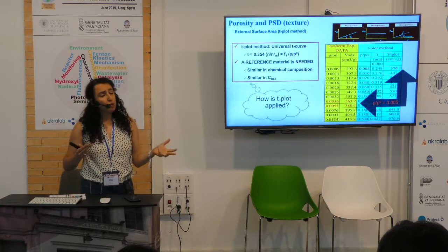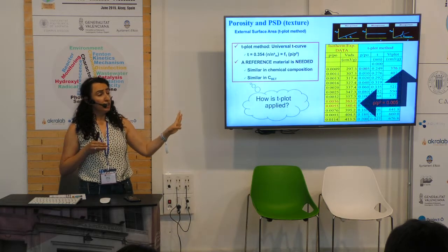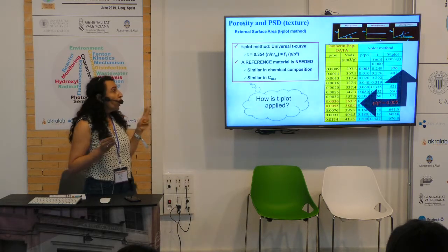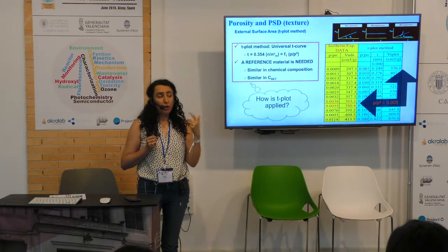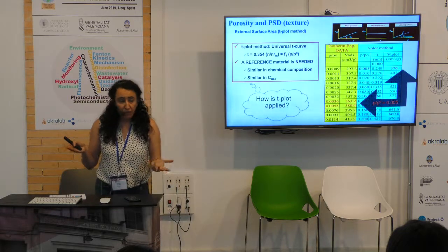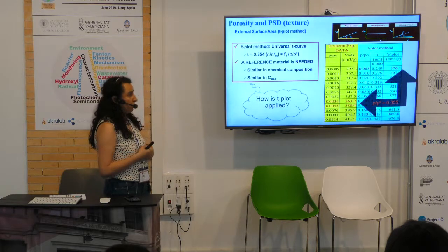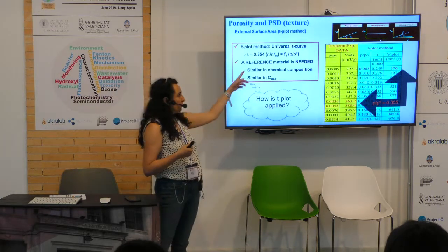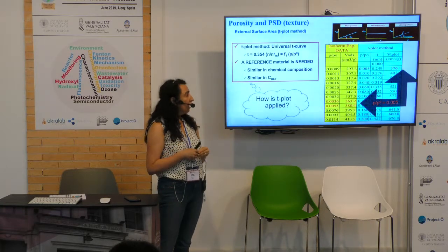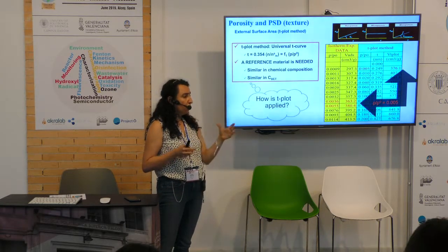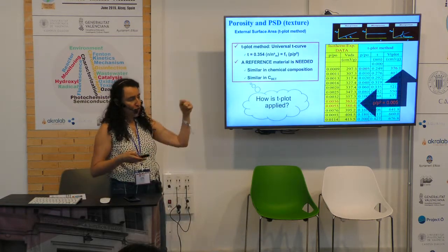material. If you don't do that, you might, for instance, not select any, so you still get numbers, but they're not meaningful. Or you can select a reference material of a silica or of a carbon, or of an alumina, and your material is not that, so you have to know which reference material is needed. These reference materials usually comply with two criteria: similar chemical composition and similar values of the affinity for the gas. And there are many of them in the literature,